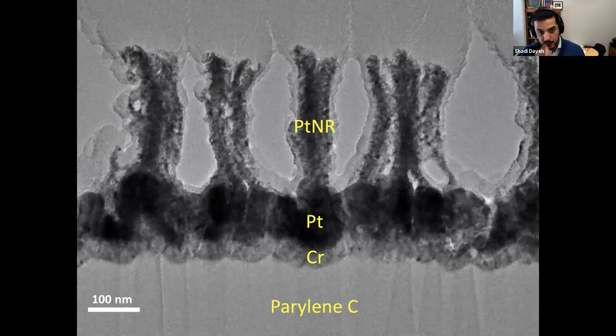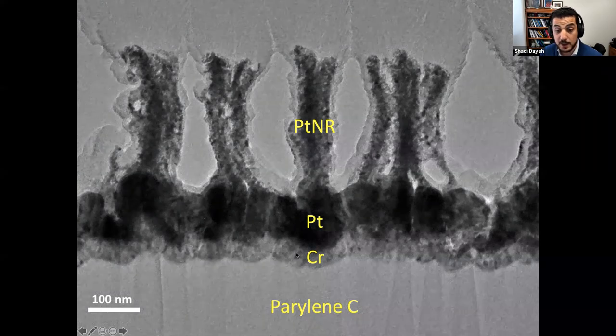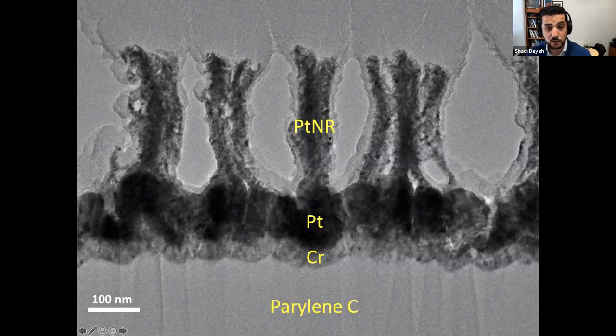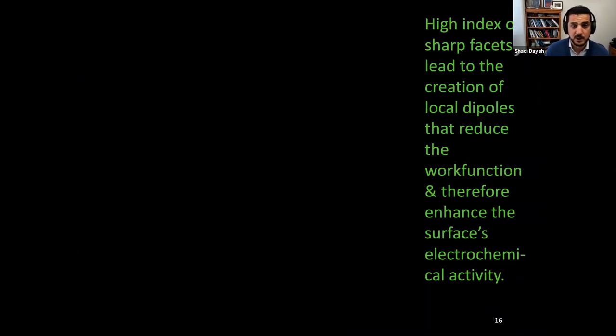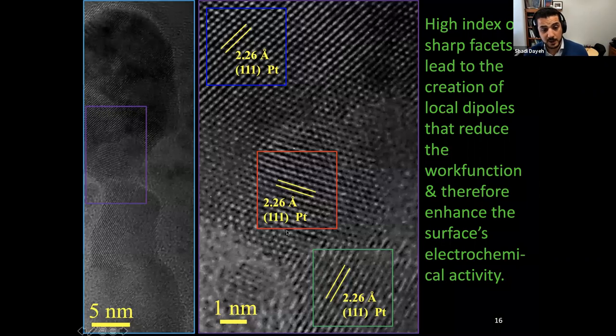And this is a cross-sectional TEM image of these rods, showing basically the structure on parylene. We have an adhesion layer of chromium and then a planar layer of platinum. And then on top, we have the rods, which are also porous, and that enhances their surface area. In addition, they have a large number of high order facets, or sharp corners, in their surface morphology.